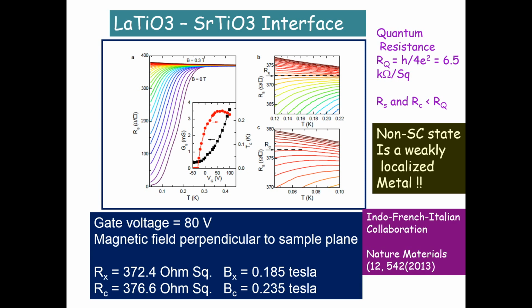Now if I expand this portion somewhere here, it turns out that I have a critical value of the magnetic field at which the sheet resistance becomes independent of temperature. That's an indication of a continuous quantum phase transition. So I can define this resistance at which this happens as Rx, which is roughly about 372 ohm per square. And the corresponding field at which this happens is this much.